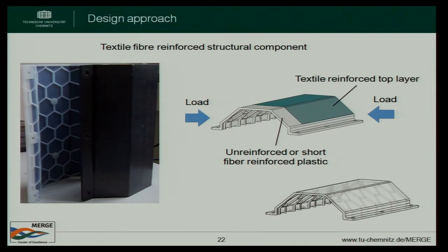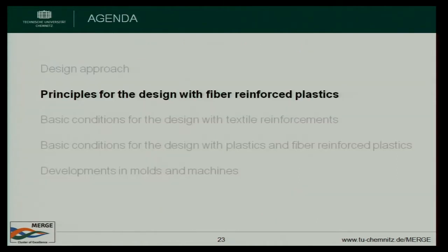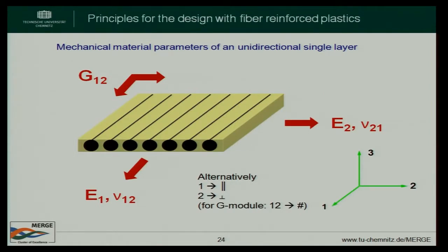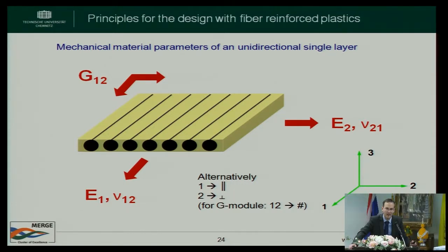And now to make something like this, we can make it in plastics. So we know our mechanical properties we have, let's say tensile modulus, tensile strength. We know some impact properties from the pure plastic. In this case, it's in polypropylene, but it's not enough. We need some strengthening of the part to get a higher stiffness and higher strength. So first is, as I mentioned already, fibers for the reinforcement have a reinforcement effect only in fiber direction.